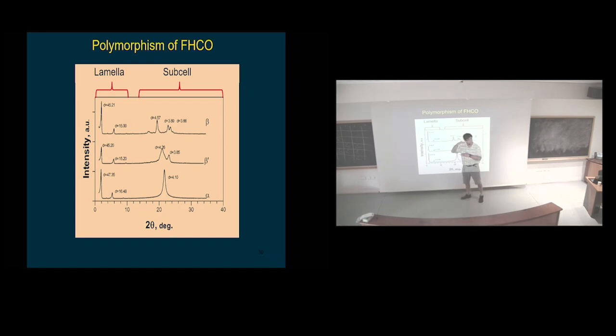These are the lamella I talked to you about. And so the lamella here are like 47 angstroms, and these are lamellar faces. And if you get peaks from a lamellar face, they space as 1, 1/2, 1/3, 1/4. They're like that, integers. So 45 divided by 3, 15. So this is the 001 reflection. This is the 003 reflection. And you can get many more, as I'll show you for chocolate.